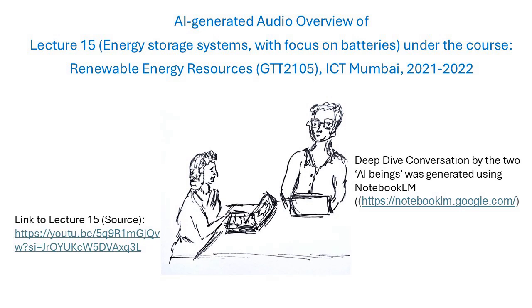Yoshino built on work by Yazami, who'd shown lithium could intercalate into graphite. Yoshino's focus was finding a stable carbon material for the anode, one that wouldn't react badly with a non-aqueous electrolyte. Because apparently standard graphite reacted with the common solvent, propylene carbonate, causing decomposition, gas buildup, and killing the battery. Exactly. So Yoshino meticulously researched different types of carbon, looking at density, crystal structure, to find one that worked reliably and safely. A materials science triumph. He found a carbon that could host the lithium ions without those side reactions.